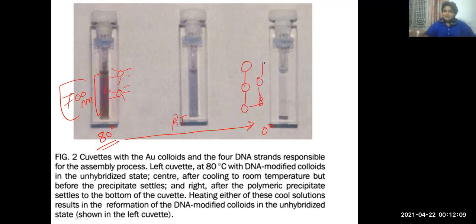The moment there is assembly, you can actually check this at 260 nanometer. 260 nanometer is the absorbance maxima for DNA. So here the characteristic absorbance is by DNA. Here the maximal absorbance is by gold nanoparticles. So if I consider, say, one of these wavelengths, let us consider 700 nanometers, then I cycle the temperature. Since we are using a thermocycler, let us cycle it from 0 to 80, 80 to 0, 0 to 80, and so on and so forth.